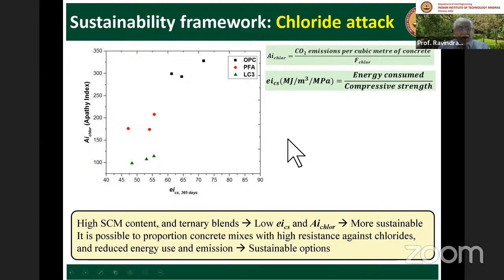So the concretes that I've discussed before are plotted here. On the y-axis, I have the apathy index. The apathy index definition is given here. On the x-axis, I have the energy intensity and the definition is given here. Whatever is going in this direction, closest to the origin, we consider is more sustainable. And clearly, you see that LC3 falls here. Out of all these, very clearly, the LC3 comes out most sustainable, followed by fly ash, followed by the OPC concretes. So if you look only at M30, all these three are M30. They satisfy your requirements from the design point of view. They're all workable. Very clearly, the M30 made with LC3 is more sustainable than the other two.